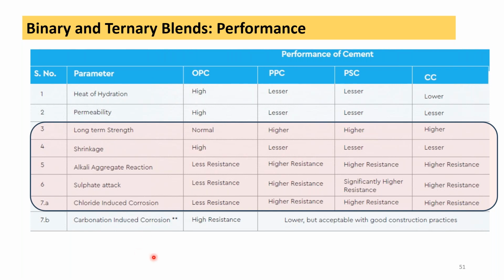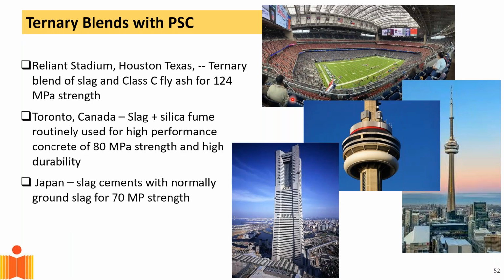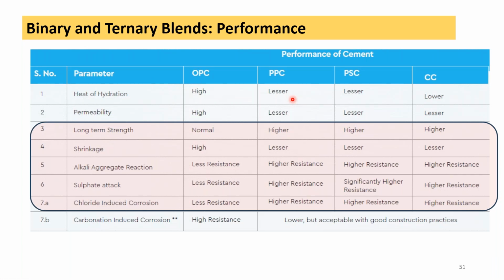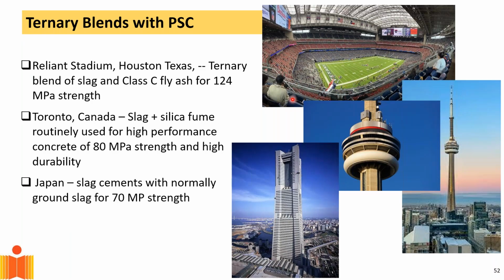The only thing that perhaps one needs to look at carefully is the carbonation induced corrosion, where it has been reported that PPC and PSC perhaps have a higher risk of carbonation induced corrosion. Now, what about using blends of slag and fly ash? So where I can benefit from both.